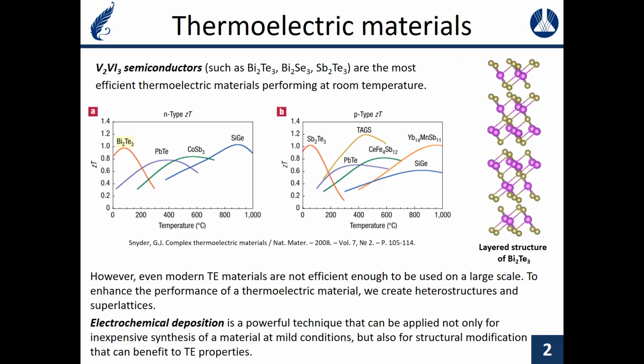The prospective way to improve significantly the figure of merit of the layered structure of bismuth telluride consists in the reduction of lattice thermal conductivity by introducing interlayers between Bi2Te3 quintuples. In this work, we have developed the electrochemical synthesis of the simplest superlattice structure based on bismuth telluride, Bi2Te3-Bi superlattice with bismuth atomic bilayers.